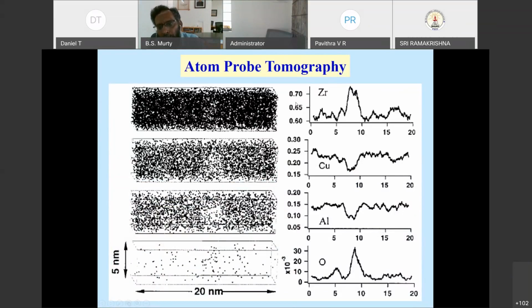The top one is zirconium, copper, aluminum, and oxygen. And this particular small particle, which is about 2 nanometers in size, has a lot of oxygen in it. Of course, those days, the atom probe that was available was not a very efficient atom probe. With a lot of struggle, when you wait for 24 hours of collecting atoms from the sample, you are able to collect about 400,000 or 500,000 atoms.